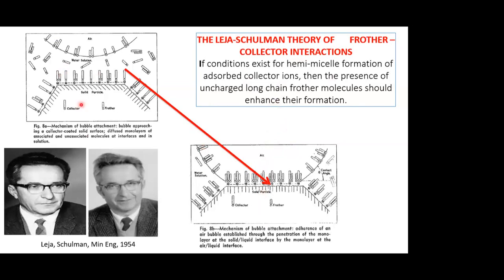And of course, what this cartoon is showing is that here we have the air surface, and of course, as we all know, we have the alkyl group in the air phase, and we have the OH of the alcohol at the water interface. And here we have collectors on the mineral particle surface in a normal fashion. So we have the adsorption, could be a xanthate or whatever, with the alkyl group. And so what this theory proposes is that when the air bubble meets the particle, we get hemi-micelles forming between the frother molecules and the collector molecules. It's somewhat contentious. There are some people who swear by this.